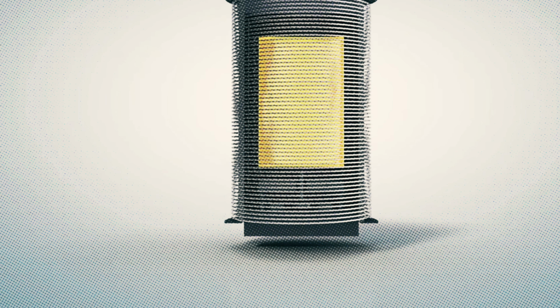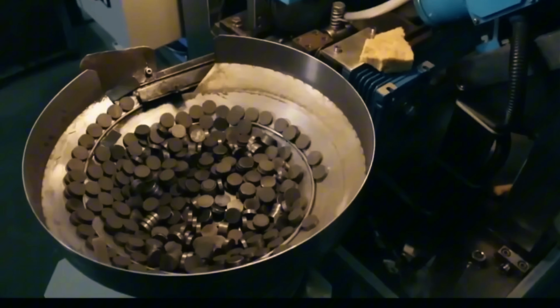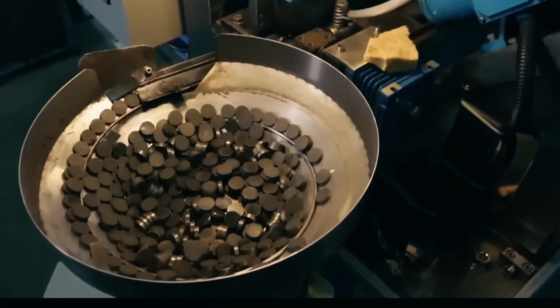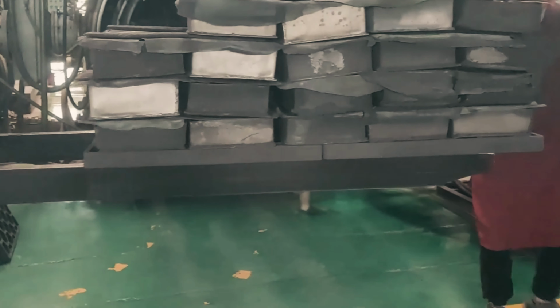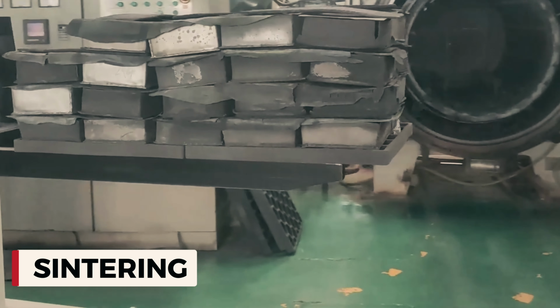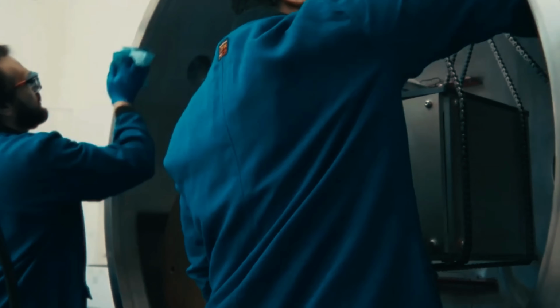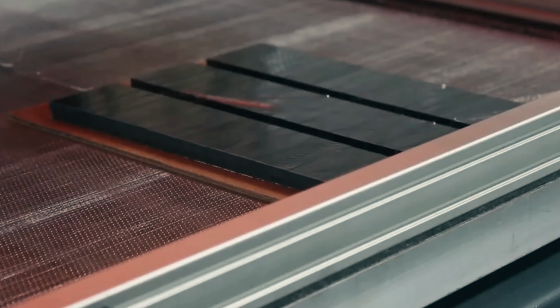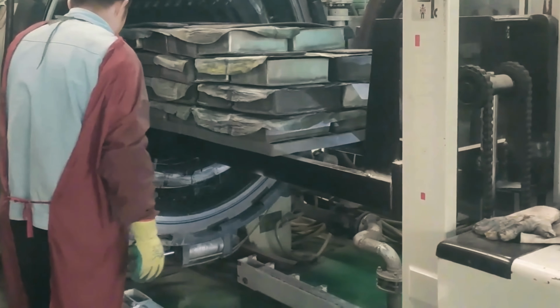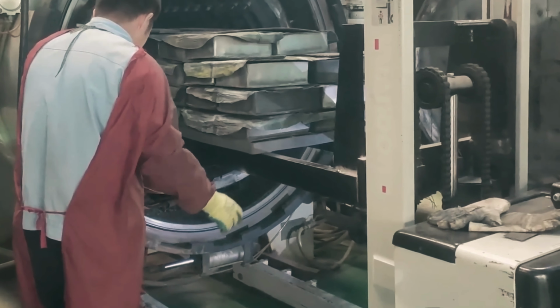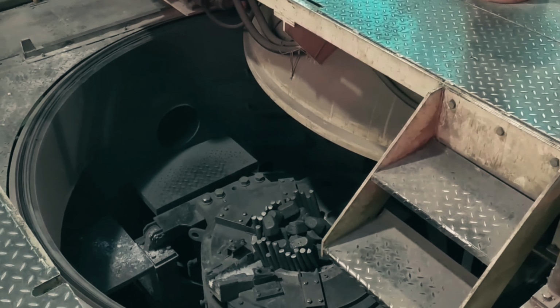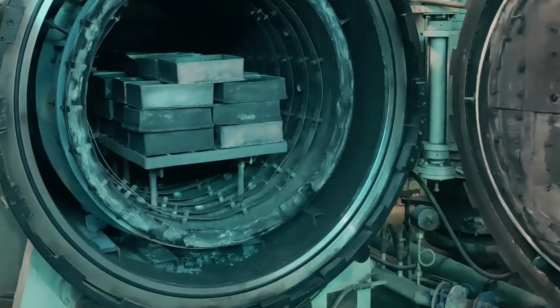While still aligned inside that magnetic field, the powder is compacted under enormous mechanical pressure, sometimes exceeding 100 megapascals, squeezing the particles together into a dense, solid shape. From here, the piece moves into a furnace again for a process called sintering. Instead of fully melting the material, it's heated to just below its melting point and held there. The particles fuse together at a molecular level, becoming one dense, unified block, all without disturbing the microscopic alignment that was locked in during pressing.